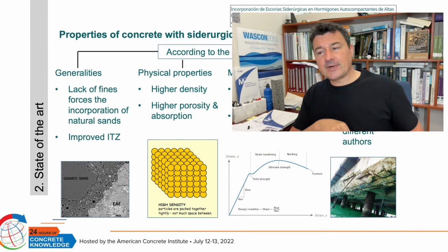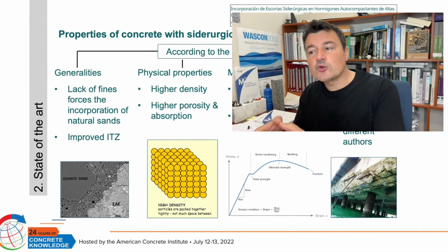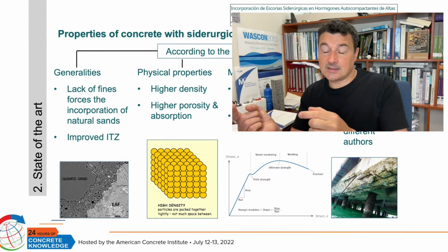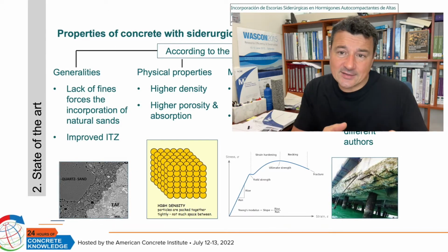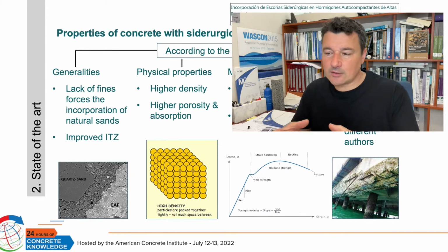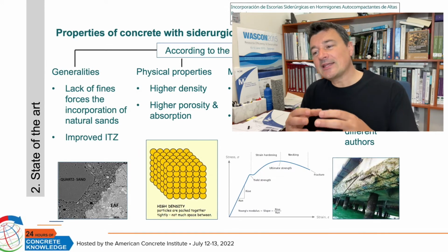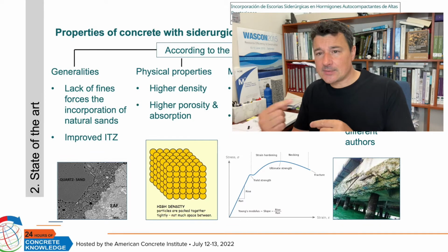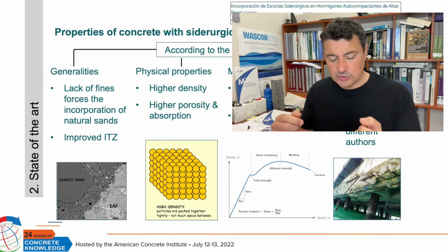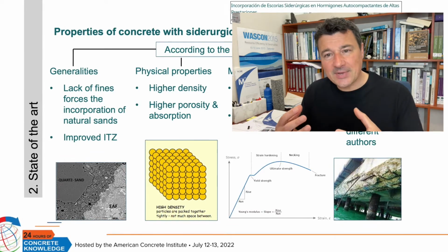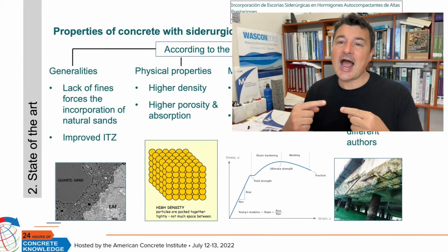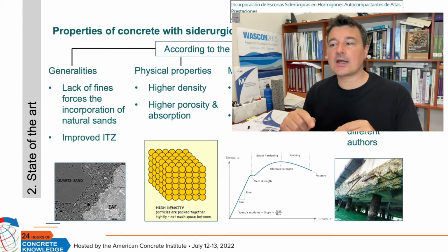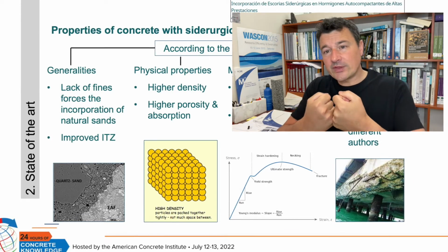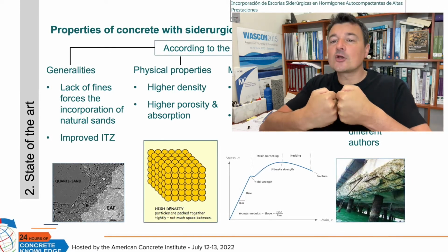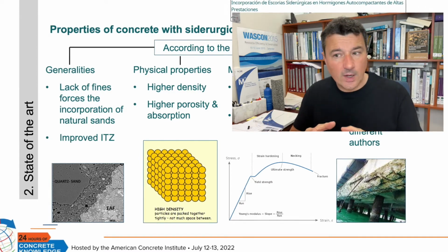Regarding the physical properties, of course, the use of siderurgical aggregate increases the density of the material if we compare it with the density of the standard concrete. And also, it presents higher porosity and absorption, but it is due because the volume of cement paste sometimes is higher in the siderurgical aggregate concrete because the cavernosity of the siderurgical aggregate doesn't close the volume very well.